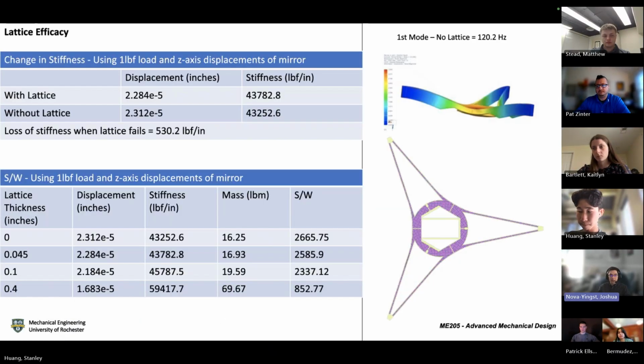So because we had such a difference of margin of safety, lattice versus no lattice, our thought was, okay, when we do lose the lattice, since the lattice yields before the part does, how much does the part suffer? From what we found, there's only a loss of stiffness of about 530 pounds per inch, which compared to the average stiffness, which is 43,000, we felt was negligible. So it seems like the lattice, at least this particular lattice in this particular geometry, is little more than just dead weight.